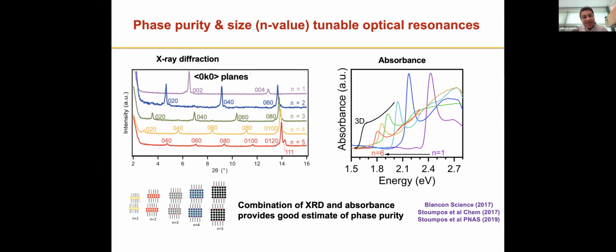You can then take this pattern and also perform absorbance measurements on these crystals. And you can see a nice ground state excitonic feature. As you go from N1 to N6, you see that your exciton binding energy, or the peak height of these excitons, is decreasing. That makes sense because you're decreasing the quantum confinement in these materials. But you also see that these are all very nice single peaks, which correspond to the N value that you have. So by combining these two measurements, you can get a very good estimate of whether the batch of crystals you made are phase pure, or do they have mixtures of other N values that exist.